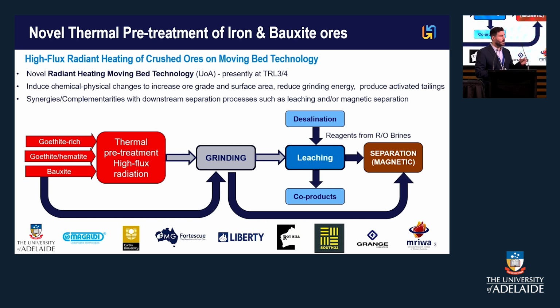We do that through high flux radiation heating, the reason being that this can be provided through a series of renewable energy sources. As you can see from the slide, the idea is to provide the heating upstream so that we can also potentially soften up the material so it's easy to grind. And there is a lot of synergy with the work that Lina and Jacques are also leading at Curtin, because thermal treatment, of course, can be done in isolation, but there is also strong synergy with downstream recovery, such as the novel leaching from Lina or more traditional magnetic separation. So today I will give you some results on that.